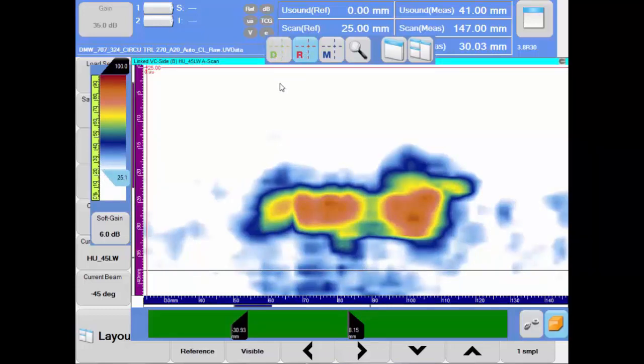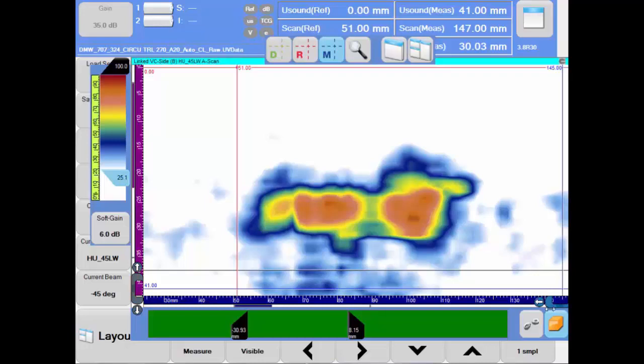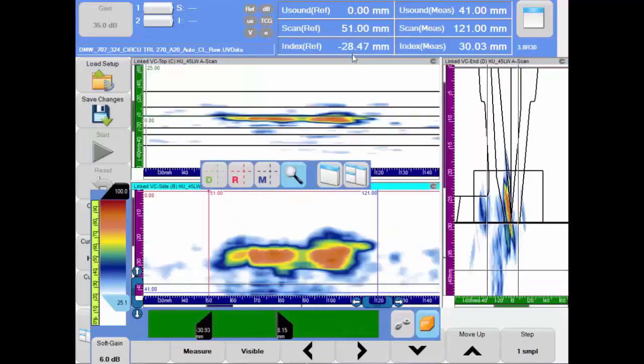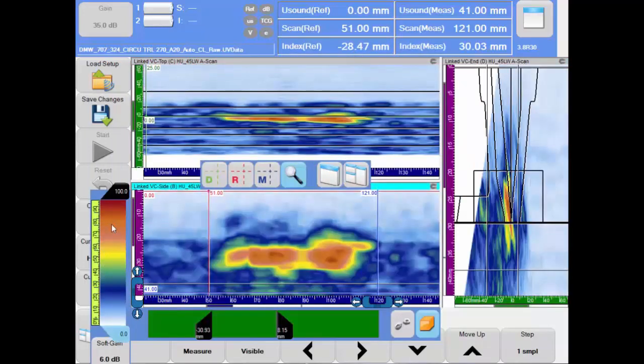The soft gain setting and the color palette editor are quick manual tools to conduct this sizing exercise. For well-resolved flaws in easier materials, the software also supports an automated length sizing process by simply positioning the cursors around the indication. For through-wall sizing, we will use the tip diffraction technique.